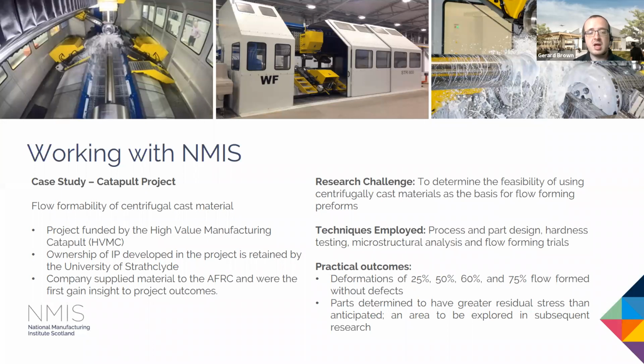experimental design, and we carried out similar testing as before, hardness testing, microstructural analysis on the parts, and obviously the flow forming trials themselves. Practical outcomes in this sense: we were able to prove that the centrifugally cast material supplied to us by our industrial partner could be deformed up to 75% without any defects, which was a fantastic result. But it also did allow us to identify an area for future research, which is really key.